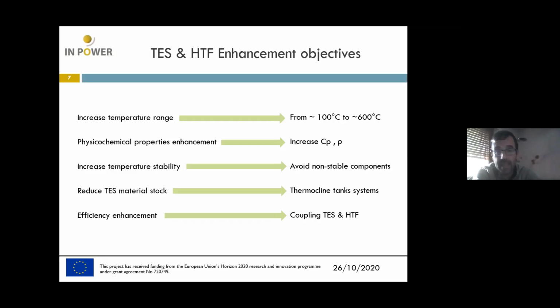Also, the reduction of stock of the TES material is a very important thing, because as you know, the CAPEX of a CSP plant suffers a lot from this matter, because it represents about 20 to 25% of total CAPEX. So if we can reduce a bit the stock of this material, it's directly a cost reduction of the CSP plant. Also, with thermocline tank systems, it can be reduced by means of having only one tank, not two tanks. So that's another CAPEX reduction.